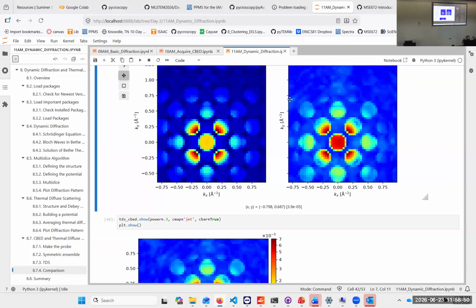But the strengths of the Kikuchi lines can actually be quantitatively evaluated here. So you can use a Kikuchi line to evaluate how much phonon you have. Yes, and that is sometimes done. You want to suppress the phonons a little bit, and then you can go to liquid nitrogen temperatures, and you will definitely see the effect.